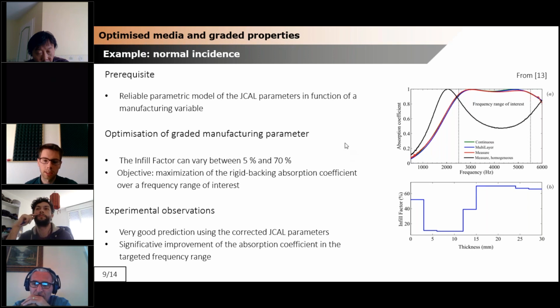What is nice here is that we can optimize the gradient of properties of a material numerically, but what is even nicer is that, as we considered the manufacturing defects and their impact on the acoustic intrinsic parameters, once we 3D print the sample that is optimized with a gradient of properties, its absorption curve is the one that was predicted.